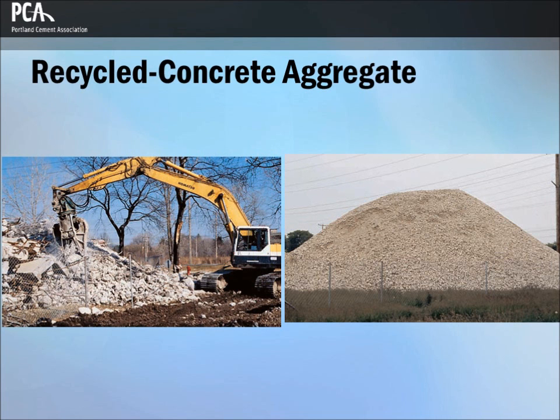Recycled concrete is simply old concrete that has been crushed to produce aggregate. The procedure involves demolishing and removing the existing concrete, crushing the material in primary and secondary crushers, removing reinforcing steel and other embedded items, grading and washing, and stockpiling the resulting coarse and fine aggregate. Recycled concrete aggregate is primarily used in pavement reconstruction. It has been satisfactorily used as aggregate in granular sub-base, lean concrete sub-base, soil cement, and in new concrete as the primary source of aggregate or as a partial replacement of new aggregate.